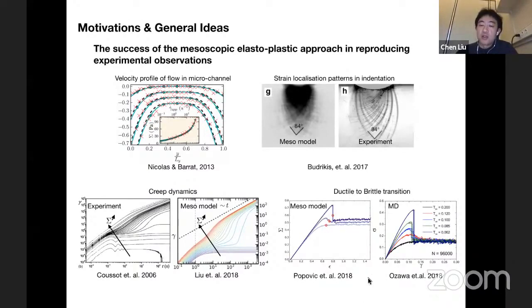The last one is the recent study on the transient behavior that depends actually on the thermal history of the preparation of the samples. So here you see that as the sample is equilibrated at different temperatures, the overshoot will depend on this temperature.